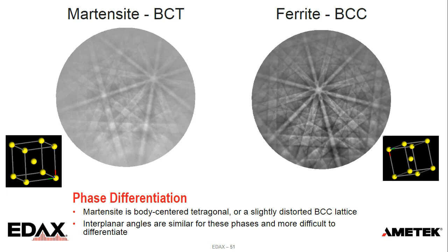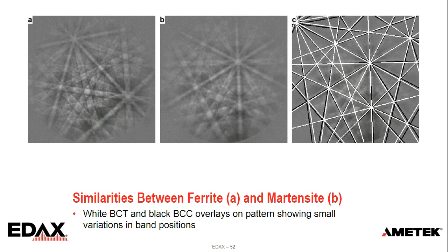And this just shows an example of this. So there are our ferrite and martensite patterns again. But in the image for the martensite pattern on the right, the C image, it shows the white martensitic overlay and the black ferritic overlay on the same pattern. You can see at places the white and black lines are essentially lined up, and the shifts between them are very small. They're very subtle shifts between the two. So it's difficult for the Hough to reliably differentiate. It can differentiate, but it's not always 100%.